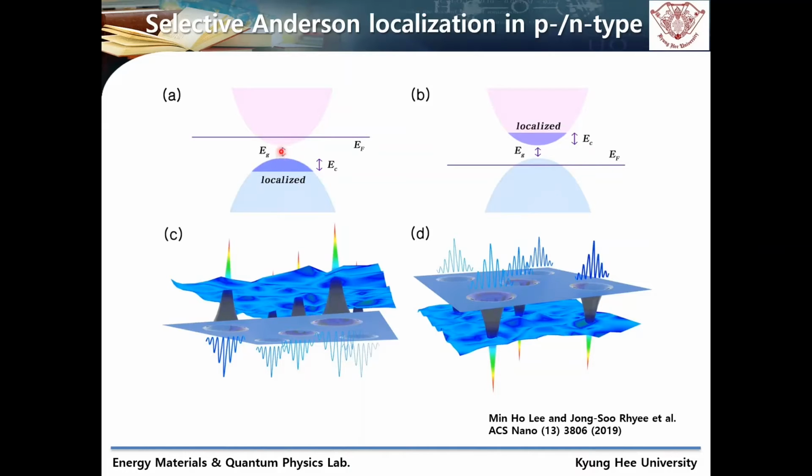For example, the effective energy band gap is the intrinsic band gap plus the cutoff energy. This large energy band gap can increase the Seebeck coefficient, and the bipolar transport of carriers can be blocked by this strong selective charge localization.